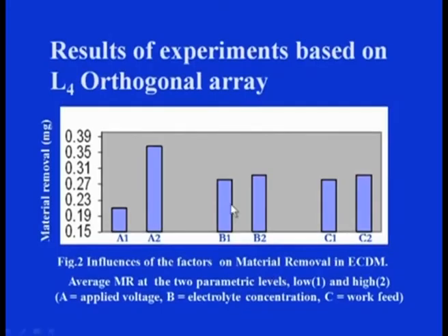Now, let us move to a case study which describes the machining of glass using this particular process, ECDM. These experiments were carried out in IIT Roorkee. The material used was soda lime glass and the tool material was copper and stainless steel. So, this figure on the screen shows the results of the experiments conducted using this ECDM process, in which the effect of different parameters like applied voltage, electrolyte concentration and work feed are shown on the material removal.